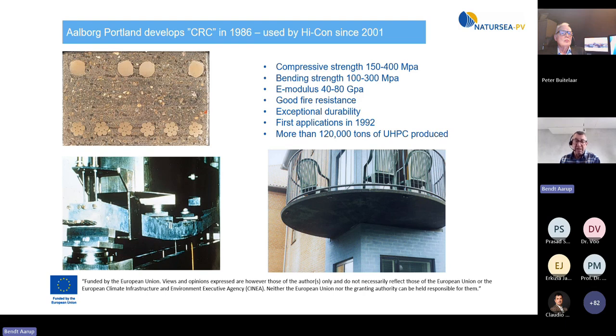Young's modulus, again, depending on the type of aggregate we use, but we're typically around 45 gigapascals with our normal mix. We have to have a good fire resistance, as most of our products are used in buildings. And when we use slender elements and we want to include rebars, we have to have very good durability, because we normally have a cover to the reinforcement of 10 to 15 millimeters.